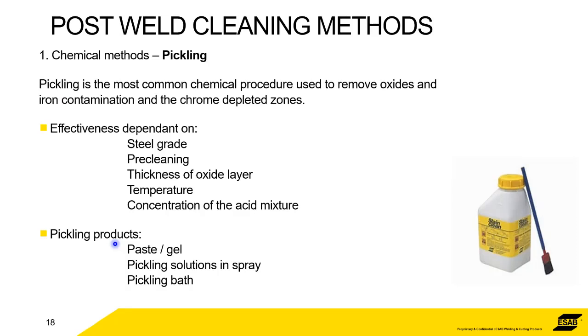We've said there it will remove the oxides and the chrome depleted zone, but it'll also remove iron contamination. Didn't specifically mention it, but things like grinding dust and sparks are again very hot. Sparks will take away the chrome oxide layer on top of the base metal. And also they're traveling at great speed, so you've a high possibility of embedding slivers of metal into the surface. So the iron can actually be embedded into the surface, and something like pickling will get rid of that. That's why it's so good and so effective.